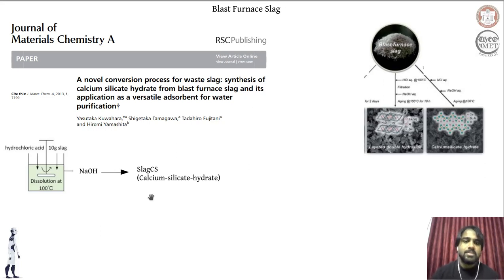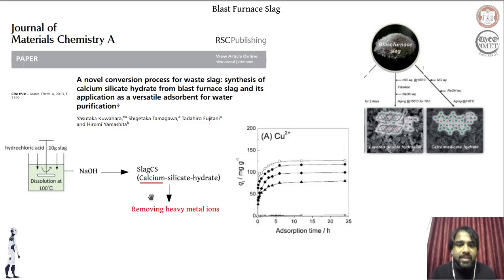Now, this calcium silicate hydrate form of blast furnace slag can be used for trapping heavy metal ions. Originally the heavy metal ions were trapped because of the electrostatic interaction between the heavy metal ions and our blast furnace slag. Now what we have is a hydrated form of calcium and a hydrated form of silica. So when you have the hydrated form of calcium, the bond that establishes between the heavy metal ion and the calcium silicate hydrate is significantly stronger, thereby increasing the efficiency of the blast furnace slag in trapping the heavy metal ions. So because again we are changing the chemical composition, the efficiency with which the heavy metal ions get trapped in the blast furnace slag also increases.